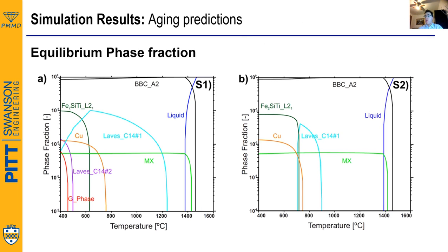Now, if we move forward to the aging predictions, we again rely on CALPHAD phase fraction. In this regard, we want to select a temperature that yields a maximum of L21 while keeping a minimum amount of Laves. Therefore, based on this phase fraction, we decided to choose the aging temperature of 500 degrees C to study the aging kinetics of this system.